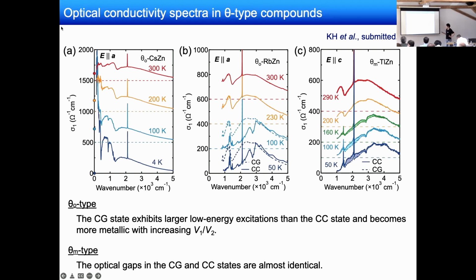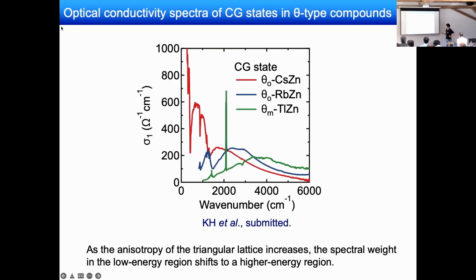Okay, so this is a comparison of the optical conductivity spectra of the charge glass states for these three different materials. As you can see, as the anisotropy of the triangular lattice increases, the spectral weight in the low energy region shifts to a higher energy region. So I want to discuss the mechanism of these different behaviors in the optical conductivity spectra.